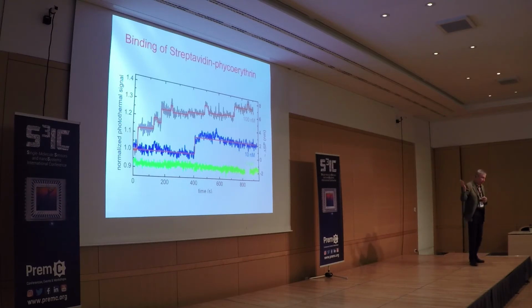So this was done at that time with photothermal detection. We are measuring the absorption of the nanorod. Nowadays, Peter is doing the same experiments by looking at scattering. You can also measure alternatively the scattering in white light or with laser light. And every time you see scattering change, this tells you one molecule is attaching to the tip of the particle and shifting the plasmon.